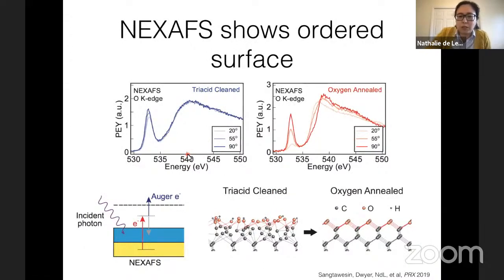So now we can turn to this direct surface spectroscopy to see what differences we can see between these surfaces. So, to my surprise, if you just look at this NEXAFS spectrum, where again what we're doing is probing the unoccupied density of states, if we zero in on the oxygen edge to look at the chemical nature of the surface termination, okay, maybe a surface spectroscopist would be really offended at this characterization, but I would say that these look very broadly similar. So I have a sharp peak here and some broad shoulder. So I think the story is not as simple as you have a ketone termination and you're turning it into an alcohol or something like that.